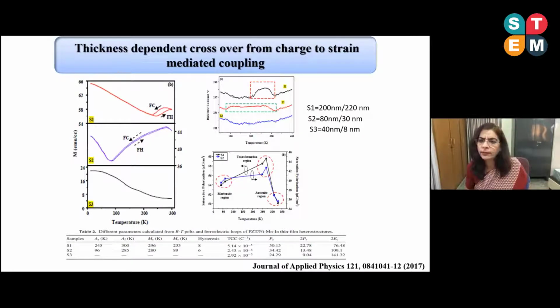What we found was that when the layers were of sufficient thickness, we were able to see strain mediated coupling, and when the thickness was very small, we got only charge mediated coupling, hovering between both strain plus charge. The reason was that when the thickness of the FSMA was less than some critical thickness, the martensite phase transformation is not complete, so there won't be a complete transfer of strain from the FSMA layer to the piezo layer, and the coupling between them is then due only to charge. These results are shown in this diagram.